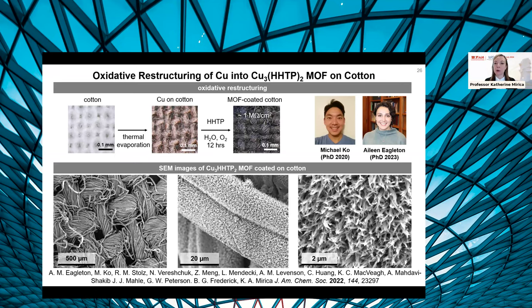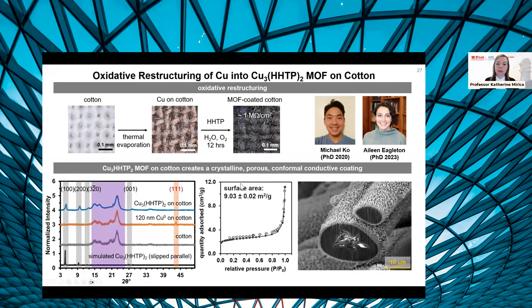adhesion that is likely promoted by chemical interactions such as hydrogen bonding to the surface of the textile of the MOF, as well as mechanical interlocking of the metal organic framework crystallites into the textile fiber, which we can see from this focused ion beam image. So the crystals kind of penetrate into the fiber and basically lock themselves in place.